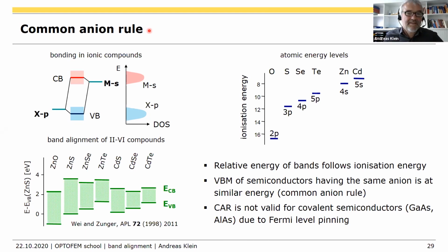Why is that the case? Where does that come from? It comes from the bonding in ionic compounds. In an ionic compound, you have your anion shell, for example, and you have your metal levels. And usually the anion levels are deeper in energy than those of the metals. And then you form an ionic bond. This is the bonding combination, and this is the anti-bonding combination. And just due to the physics of this bond, this state is mostly determined by the anion because they are closer in energy. And this one is only determined by the metals, because this is close in energy to this one.